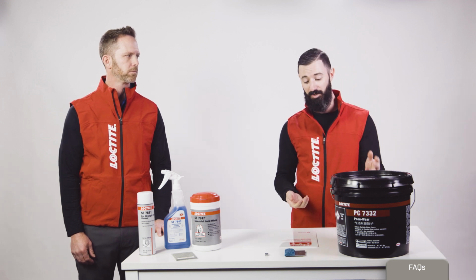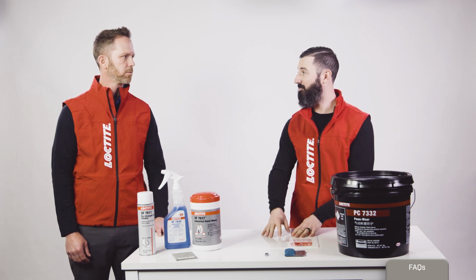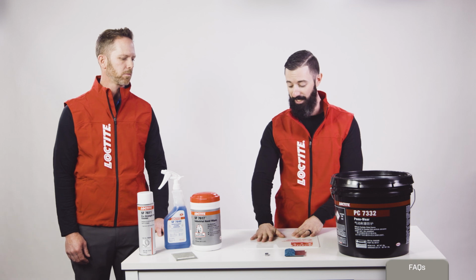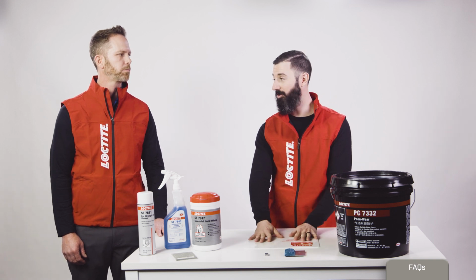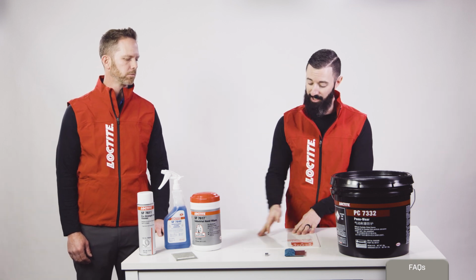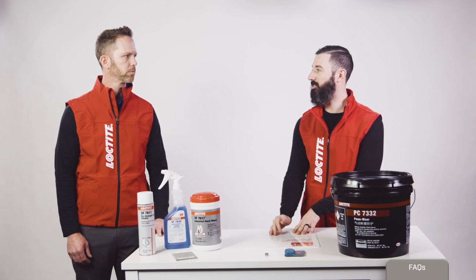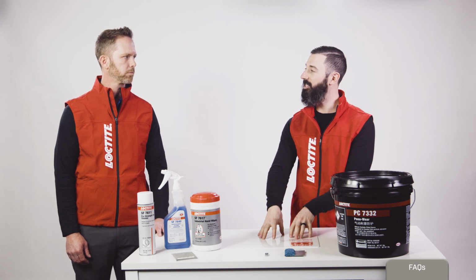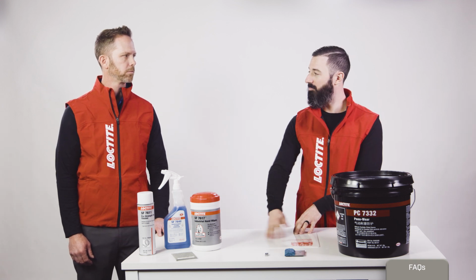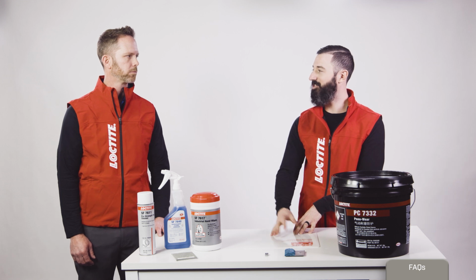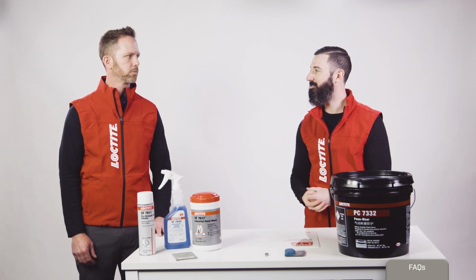In other instances, you can take out a partial mix on the mix mat like we just mentioned. You have your part A or your resin, your part B or your hardener, and you can mix the two in this figure 8 pattern to really blend together the two materials. You're looking for those striations, and if you see those, keep mixing. When you have that nice homogeneous color, you are good to go, fully mixed. Good.